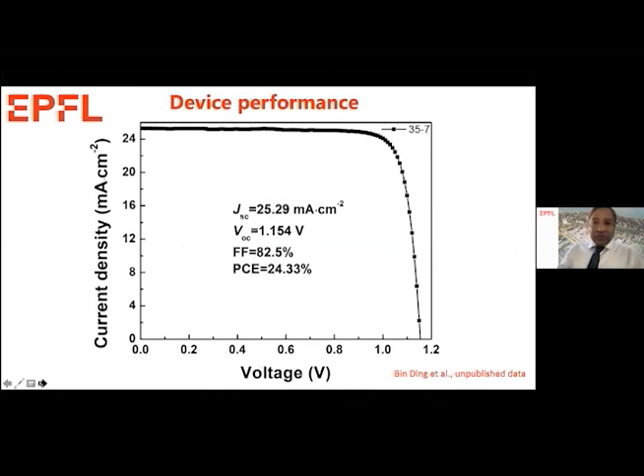Using this configuration, the highest power conversion efficiency in our lab has a short circuit current of 25 milliamps, a VOC of 1.15, a quite high fill factor of 82.5, and a power conversion efficiency of 24.33 in the lab. However, I just want to remind you that Korean groups have certified 25.5% efficiency. We are very close, but not the record efficiency.